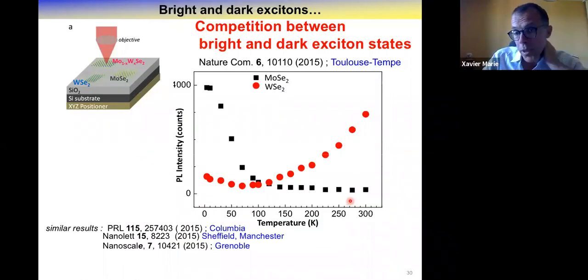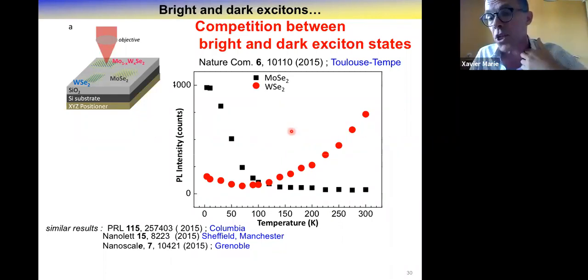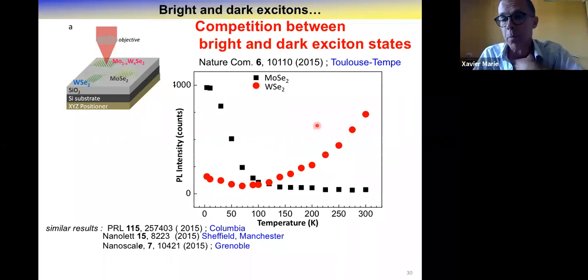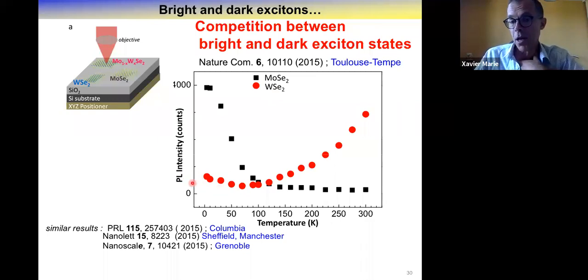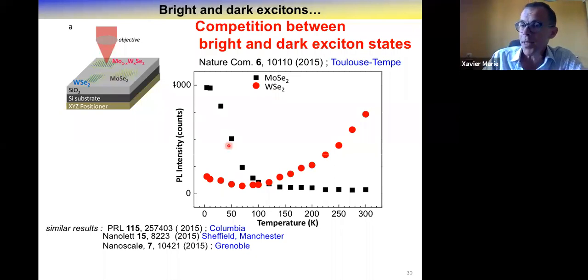So at the beginning, what we did together, and many groups did this, is to compare just the radiative efficiency as a function of temperature. What do you expect? In WSe2, at low temperature, you expect to populate the dark exciton. So you expect, as it is measured here, a rather weak luminescence intensity at low temperature. When you raise the temperature, what we see, surprisingly compared to many semiconductors, is more luminescence intensity at room temperature compared to low temperature. And this is an indication of this fine structure of the exciton, where at low temperature you populate the dark exciton, and at high temperature you start to populate the bright one and you recover